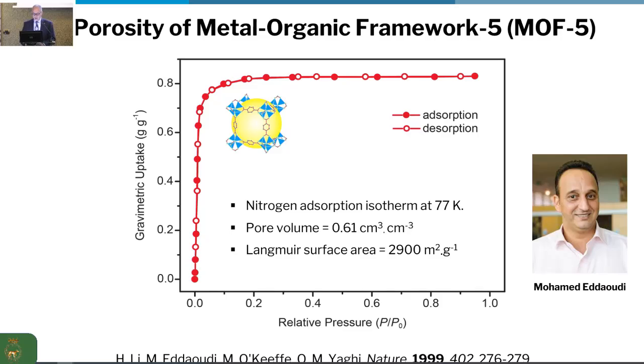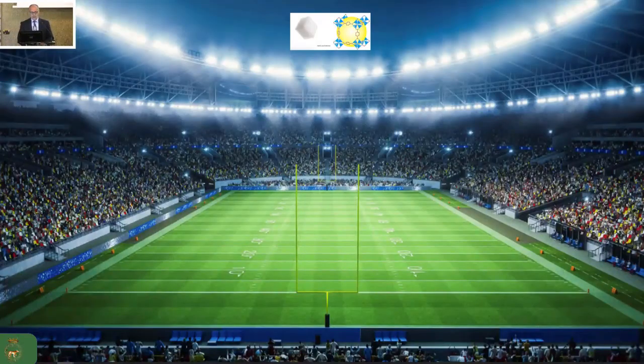And this is Mohammed again, showed that in fact these have extremely high porosity, 2,900 square meters per gram. Well, this got people's attention, not only the beauty of the structure, but also the fact that the surface area was at least 6 times more than the most porous structure previously reported. So this was really, really exciting. In fact, 1 gram of this material, which wouldn't be larger than a European sugar cube, encompasses as much space as an entire football field. Okay, think about that. So the interior is much larger than the exterior because it's filled with these microscopic pores.